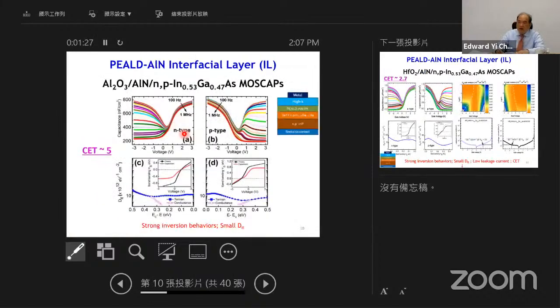So these are the MOS capacitors with remote plasma enhanced ALD material. And in this case, we use aluminum nitride as the interface layer before we put the high-K material, in this case, aluminum oxide. So this is aluminum oxide, aluminum nitride, and InGaAs PMOS, okay? And you can see that using this kind of technology, with this kind of ALD interface, the device is fully inverted, fully conversion, and with no surface pinning. And you can see that the DIT is very low, either from the experiment or theory.